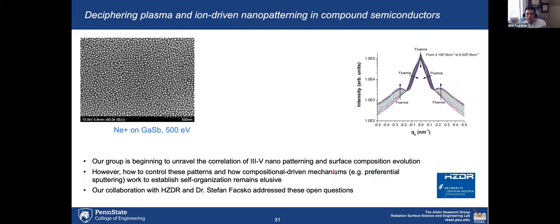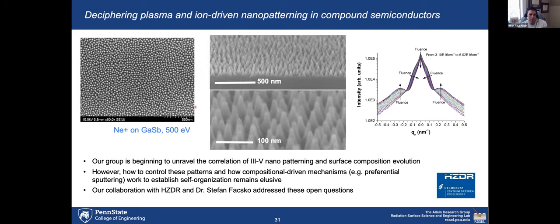So we conducted a number of studies where we irradiated gallium antimonide. This is the work that we did with Stefan Facsko and a number of my students, two of them who got their PhDs on this work, where we are creating low energy nanostructures on gallium antimonide. And we found a very interesting transition for very specific fluences. Of course, we were asking what was driving the patterning. At this high energy, 500 eV, one obvious answer was that you're etching away material, and if there are two components, you're etching material of one component more than another. That seemed very reasonable.